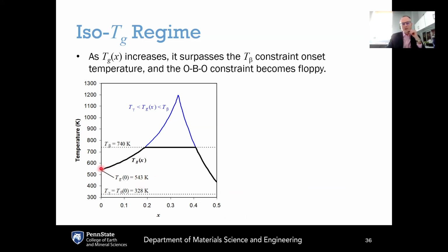And if you plot that function, you follow this black curve up, and it actually keeps going along the blue curve, peaks at the diborate composition of x equals 1/3, and then comes back down. What's happening here is that the initial addition of alkali is converting boron from threefold to fourfold coordination. That increases the connectivity of the network, which increases the glass transition temperature until it peaks where you've got the peak concentration of tetrahedral boron, and then as you start to form non-bridging oxygens, the glass transition temperature comes back down again.